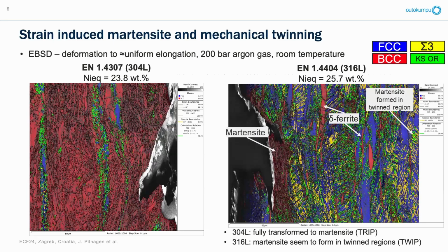And here we have an example of the stability of the austenite. So we have these EBSD maps. They are formed up to around uniform elongation in argon atmosphere at room temperature. To the left, we have this 304, which is a lower alloy grade austenitic stainless steel. And you can see it mostly transformed into martensite, which is the red color.